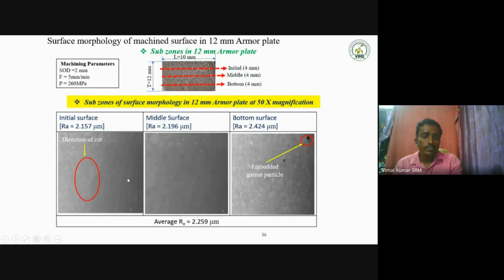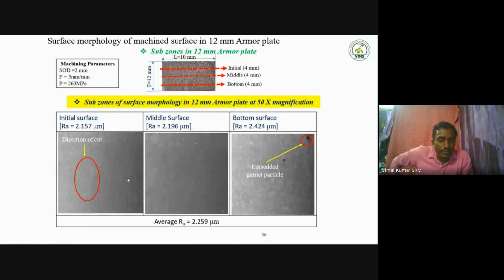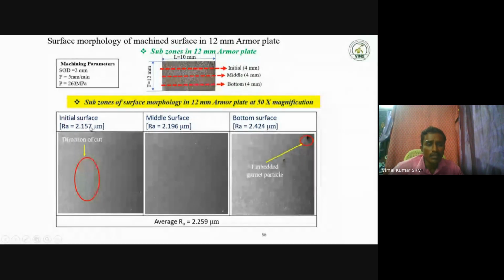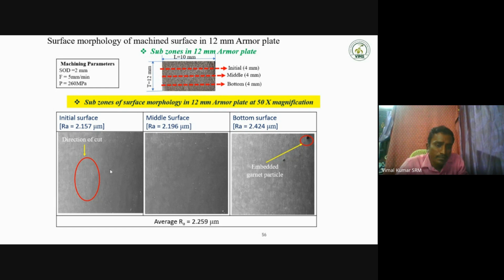Now we see some microstructure of the cut surface. Already we have seen the top surface, middle surface, and bottom surface of the 12 mm plate. Whatever surface roughness values we measured, we can check in the SEM image. Here 2.157 micrometers was identified with the physical testing equipment on the cut surface, but in the SEM image we see very minutely the direction of cut. Here the straight line is identified at a very minute level. Here the middle surface, here the bottom surface.